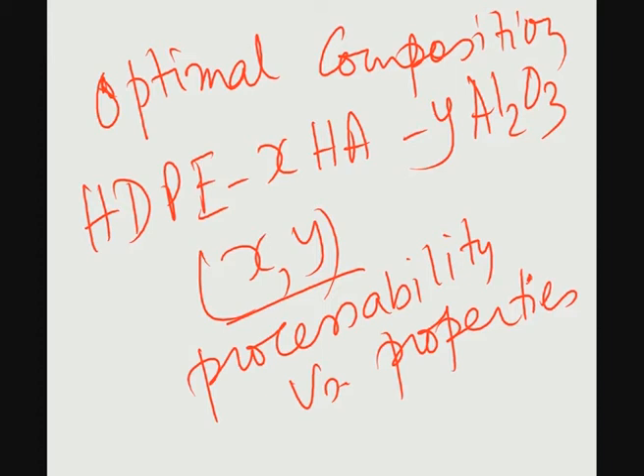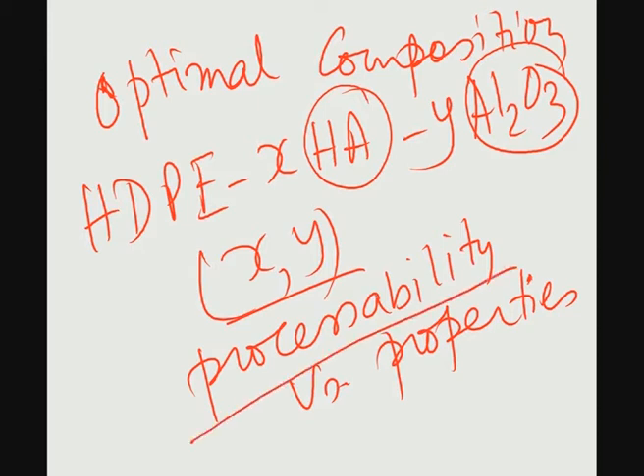Having said this, the more hydroxyapatite and alumina present in the high density polyethylene matrix, the more it will have an opposing effect on the processability or moldability, because by adding hydroxyapatite and alumina, the viscosity of the HDPE melt would increase. So, the higher the viscosity, the more difficult it is to mold these materials or to give certain shapes to them. So, you have to critically consider the processability of this material versus its properties.